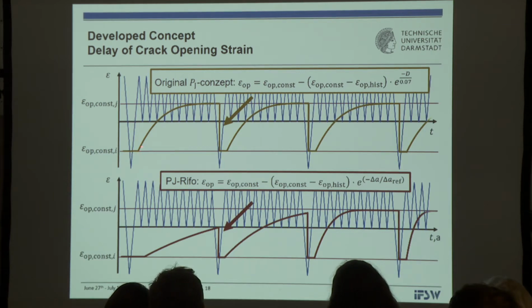And as I tried to explain previously, the crack opening strain slowly approaches the value which is associated with a small cycle. And in previous application, we used an exponential law here and used the minor type damage contribution to model this curve here, but this is physically actually not correct, and we shifted that, and we introduced that this curve of changing crack opening strains is associated with a new build crack surface. Yeah? And at the beginning, where the cracks are short, the buildup of new crack surface is very, very slow, and then this curve is flat. And in the later stages of the life, with a longer crack, the new build crack surface will be fast, and with it, the approach to the new stabilized level will also be very, very fast. So this is the change.